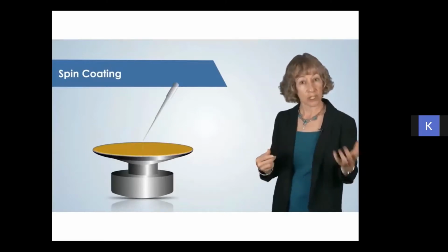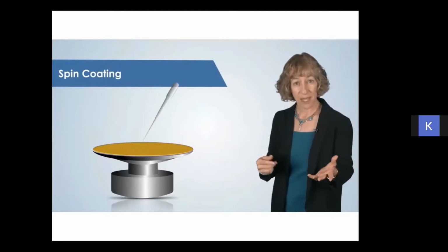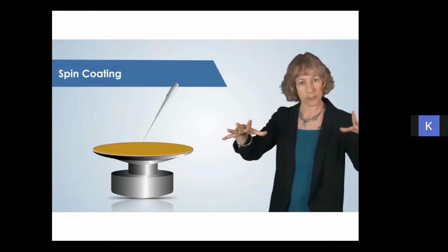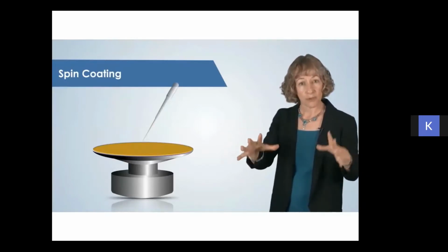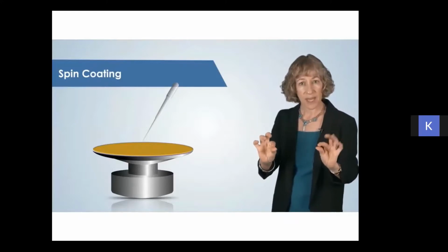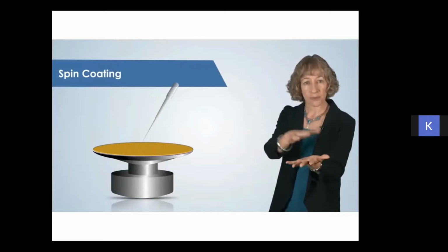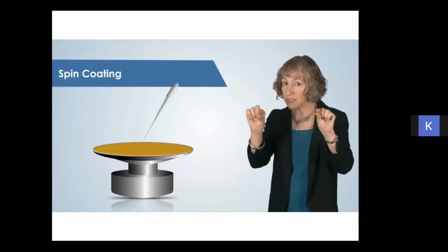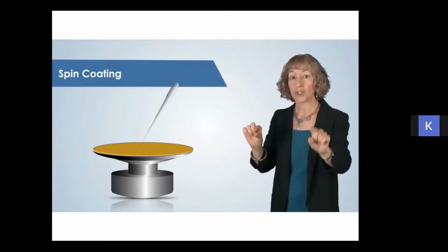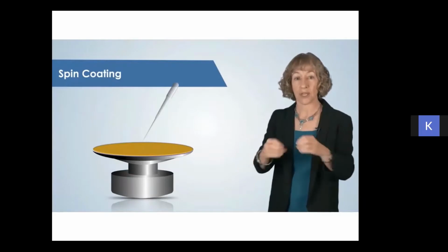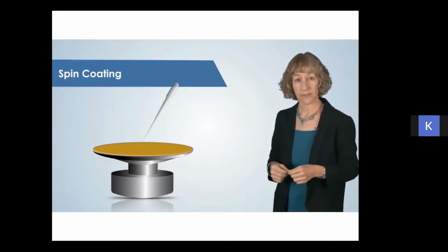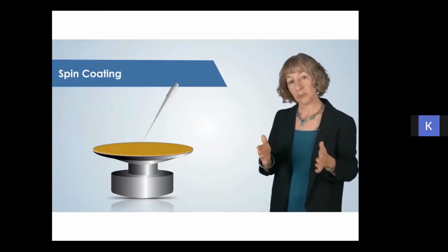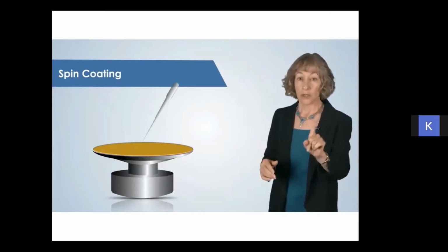So this is the spin coating process. You have to put a few milliliters of resist solution over the wafer and then spin it. You get a uniform coating. Now, if your coating is not good, non-uniformity will occur and your device quality will also get degraded. You also have to check that there should be no air bubbles inside that drop. Whenever you are dropping through a dropper, there should not be any air bubble.